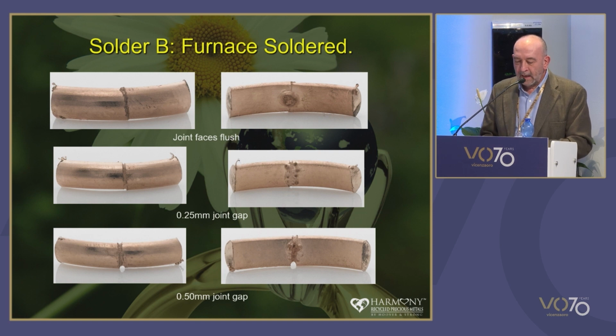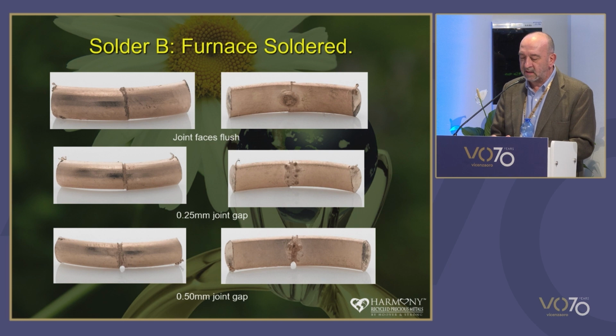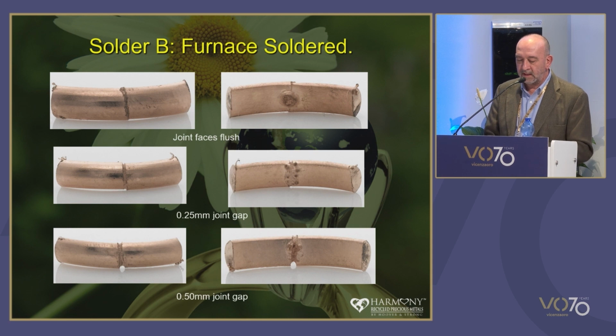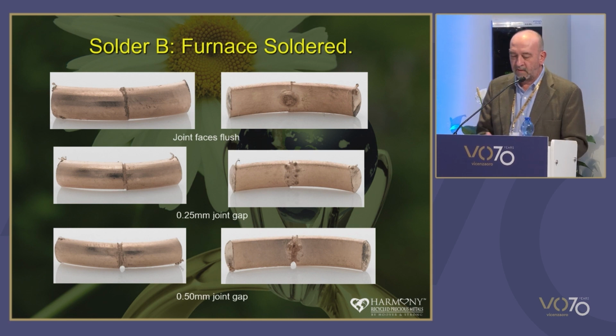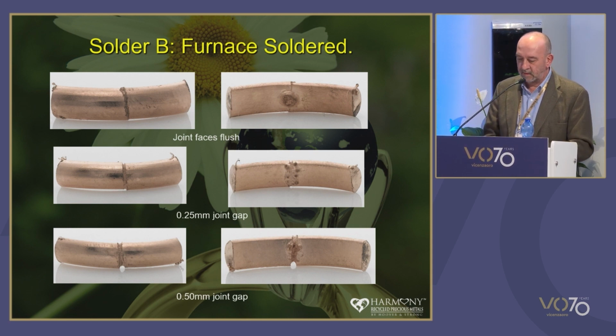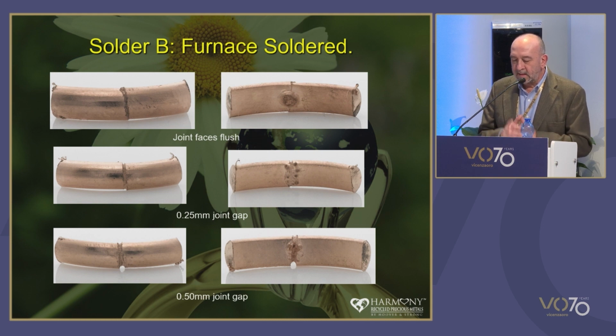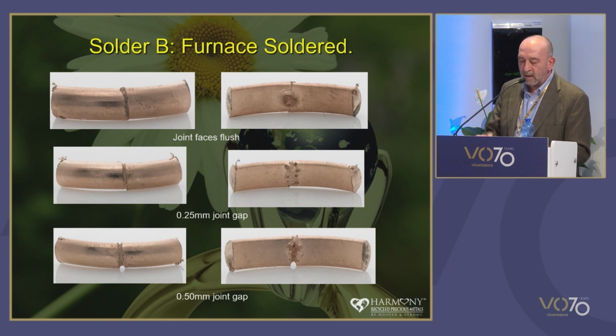So overall, hand soldering was far more forgiving than furnace soldering, giving consistent results. This doesn't mean that these solders are unsuitable for soldering in a furnace. It just means that significantly more effort needs to be made to set up the furnace. You need to set up temperatures and belt speed and dial it in for your particular application. The results also suggest that furnace soldering is going to be more susceptible to things like varying thermal loads on the furnace.